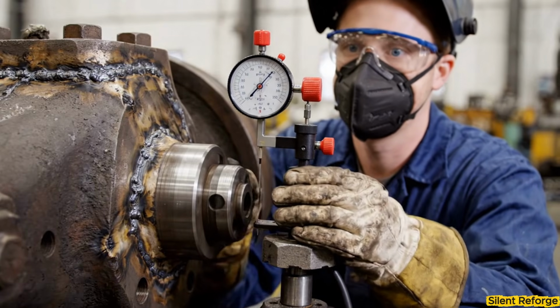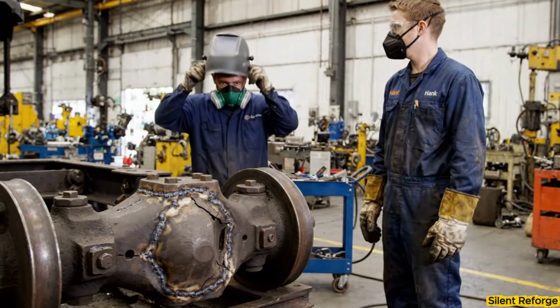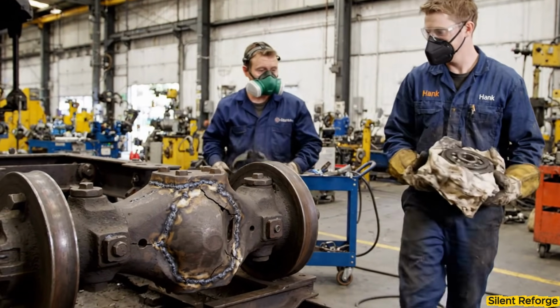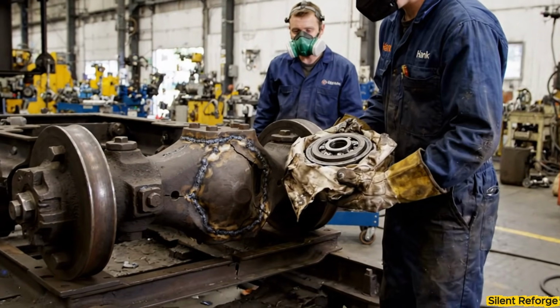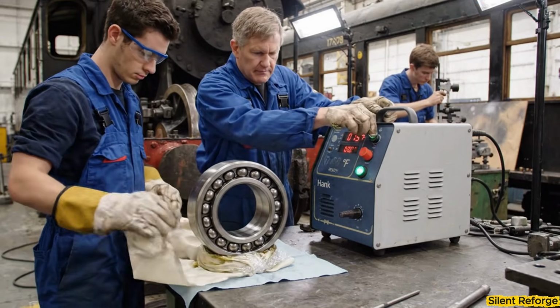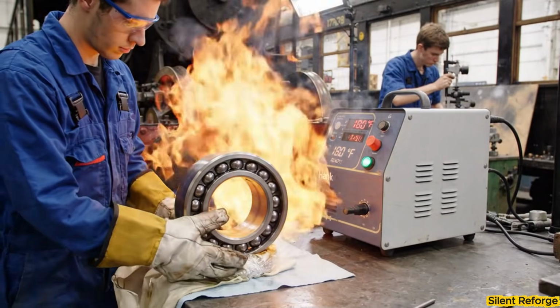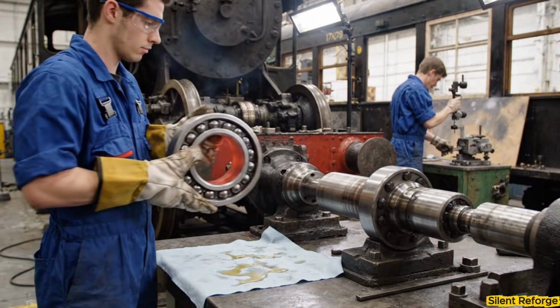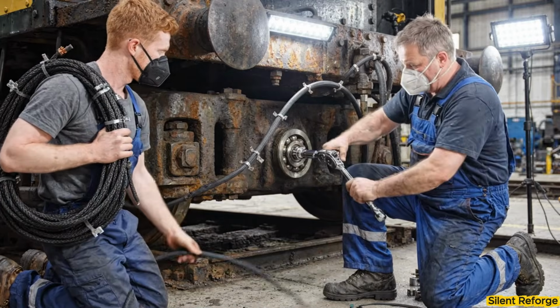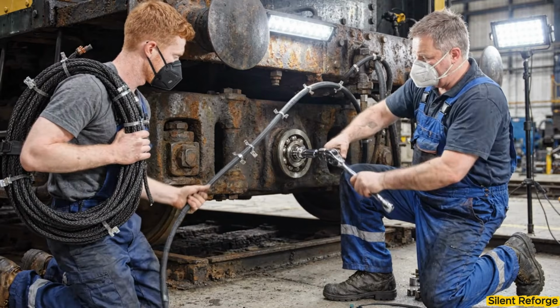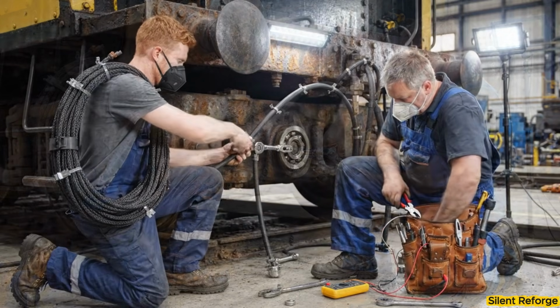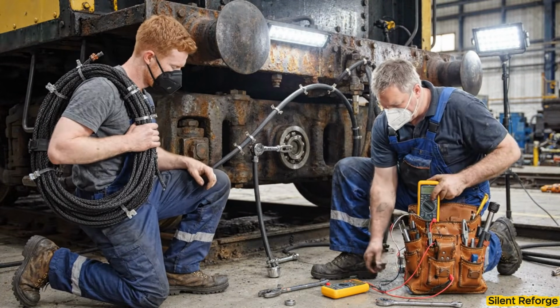Welding heat expands steel locally by as much as 40 thousandths of an inch, and if the frame is not properly fixtured during welding, that expansion can create permanent distortion. The bearing is heated to expand the inner race by approximately 2 thousandths of an inch, so it can slide onto the axle journal without interference. Bearing cap bolts are torqued to yield fasteners that must be tightened in a specific sequence to distribute the clamping force evenly.